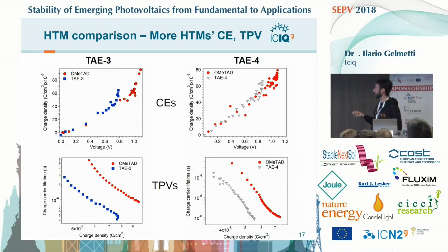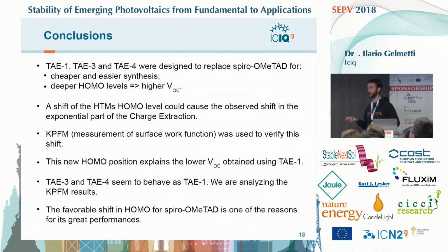But in this case, the lower voltage could also be caused by a higher recombination. As you can see, at the same charge amount, the recombination of the novel molecules is quite a bit faster. So we are now processing the results from Kelvin probe force microscopy to see if we can confirm our hypothesis also with these molecules. So in conclusion, these three molecules were designed to replace spiro-OMeTAD for cheaper and easier synthesis and for having a deeper HOMO level, so hopefully a higher open circuit voltage.